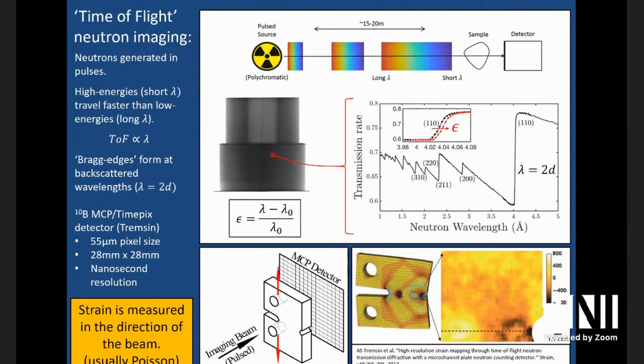There's a kind of dependence on wavelength. Really short wavelengths have lots of energy, so they'll go a long way through. Long wavelengths are the opposite, so there's a general trend anyway. And if this crystal picks off these wavelengths, we'll take a chunk out. It'll be a bit missing. And I'm not telling the whole story here. There are actually lots of these chunks missing from all the different lattice planes and whatnot. But regardless, we've got a little piece missing.